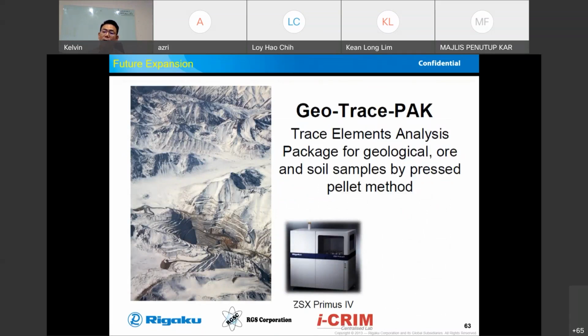Trace content itself might not be very good to do in the fusion bead. There are two reasons. Firstly, volatile elements will get vaporized when you are doing the fusion process. And for trace elements, remember when we do the fusion, we need to dilute it. Mainly, 1 gram of sample, you put in 10 grams of flux. So the dilution factor is already 10. If your sample is in ppm, then when you dilute it, it will be further reduced. So for those kinds of samples, normally we will do a press pellet so that we can measure the trace elements.